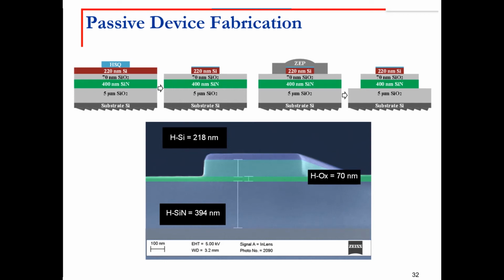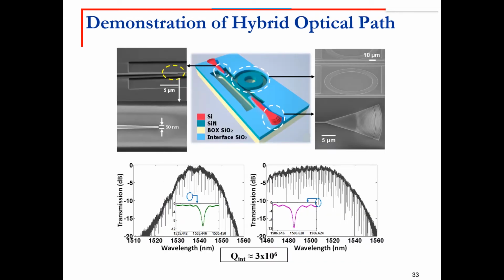So we usually fabricate devices using lithography, in our case, electron beam lithography, and etching, which is dry etching, typically using inductively coupled plasma etchers. And then after fabricating the device in silicon, we fabricate the devices in nitride, and that's an example of a fabricated device.